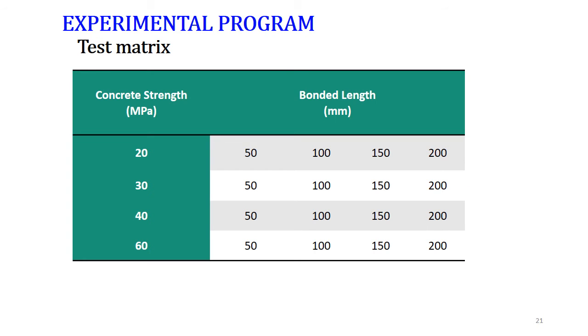This is the test matrix. There are around 32 prisms that have been developed. The concrete strengths are 20, 30, 40, and 60 megapascals, and the bonded lengths are 50 millimeter, 100 millimeter, 150, and 200 millimeter, as done for each strength. And we did 2 elements for each of the members, so we end up with that number of elements that need to be tested.